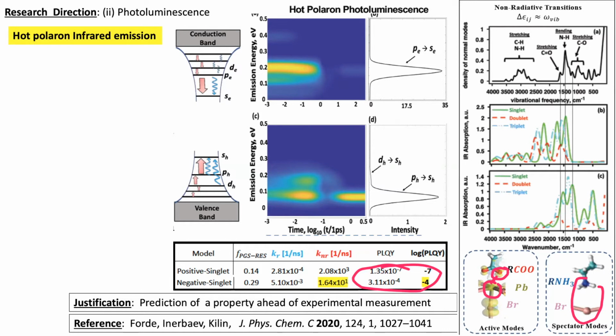So the excitation dissipates into nuclear motion quite quick, and the non-radiative lifetime of this infrared region positive polarons is much shorter than lifetime of the negative polarons.